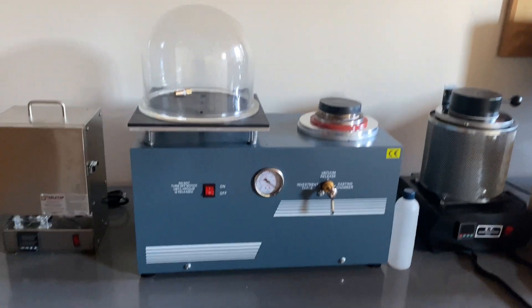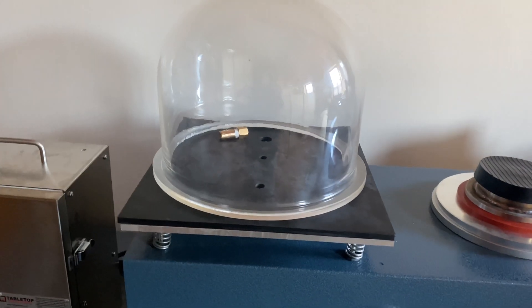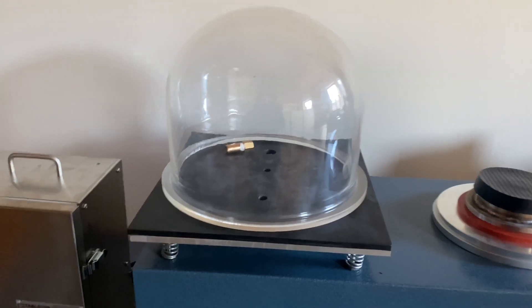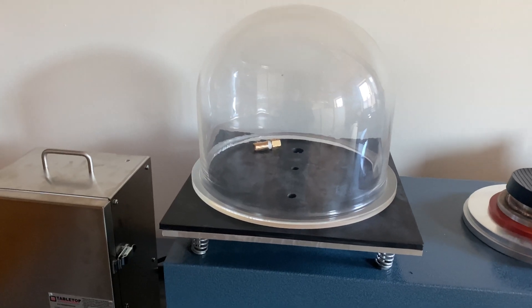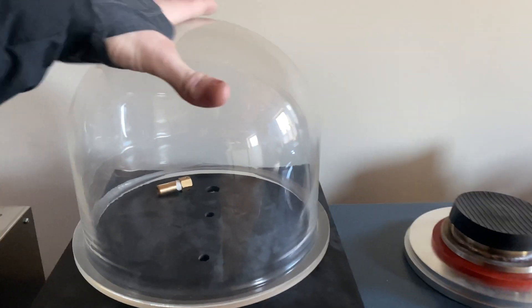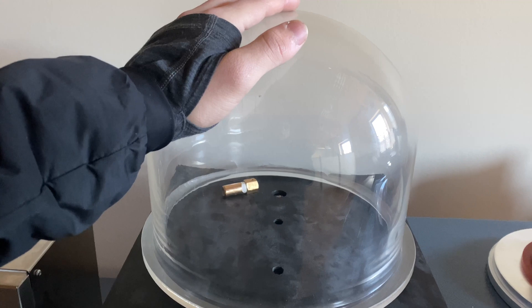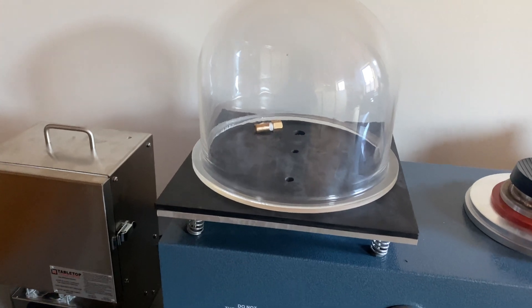In the middle we have the dual-use vacuum system, which has two purposes. The first is to get all the air out of the liquid plaster before you pour it into the flask with the mold in it. The objective is to reduce surface bubbles that stay in the liquid and attach to the surface of the object you're casting — ultimately to get a high quality surface finish and eliminate bubbles as effectively as possible. You would mix the plaster, suck out the air, pour the plaster into the mold, and then suck out the air again. That's the best way to eliminate bubbles in your mold.